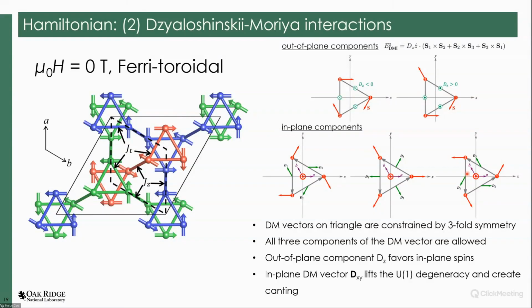But the DM vector, when it rotates, can have different chirality, a spin chirality. So the DM vector also has a chirality. The thing is, the nuclear structure is chiral. So based on symmetry, it is actually expected that the DM vector is chiral, because it comes naturally from the crystallography. So by including the DM vector, we can explain the rotation of the spin. The magnetic structure determined by neutron diffraction can also tell the various DM vector directions, and also tell the chirality of the DM vector.